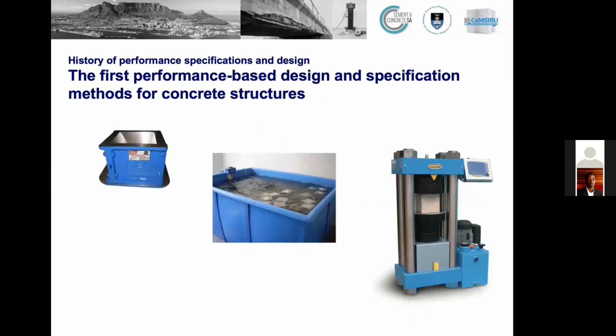And the same is true for compressive strength. So we want to model the structural performance of a concrete structure, for which we need the compressive strength, that is the behavior of the concrete under ultimate stress, which could be very different for a beam or a column or a slab and so on. And how we characterize the concrete for doing so is we cast a cube specimen, we put it in water for 28 days, and then we put it between two steel plates that move towards each other to crush the concrete. It's actually a tensile test because the concrete fails in tension, but we call this the compressive strength of concrete. And we use that in the design.